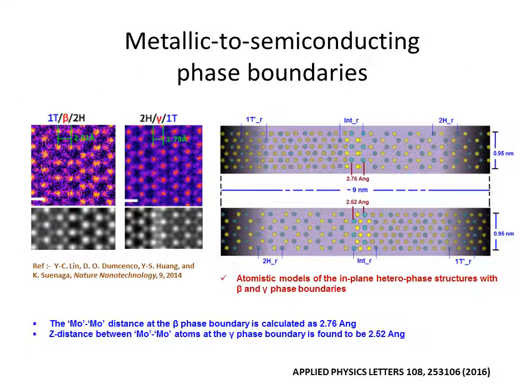In this figure, we see that the geometry optimized composite supercells having dimensions around 1 nanometer along width and 9 nanometer along the length. And finally, this forms the two distinct types of phase boundaries at the interfacing regions of 2H and 1T' planes. If we follow the atomic patterns at the phase boundaries, as illustrated by the highlighted atoms, we will find that our atomistic models of the metallic to semiconducting heterophase MoS2 structures are in good agreement with experimental observations.